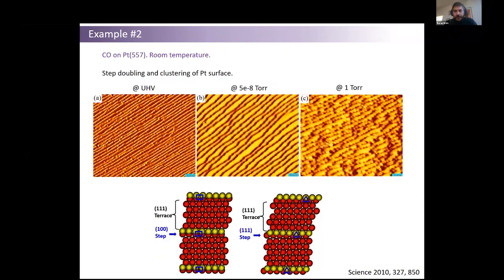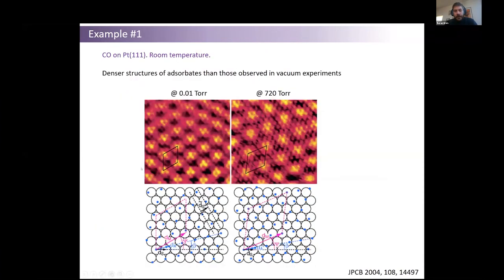Yes. This is atomically resolved images. If you don't have clustering, and if you don't have very strongly adsorbed species, you can still see the atomically resolved image of your surface. Yes, not all studies get atomically resolved images. I would say of the 50 studies, maybe 20 of them are atomically resolved.